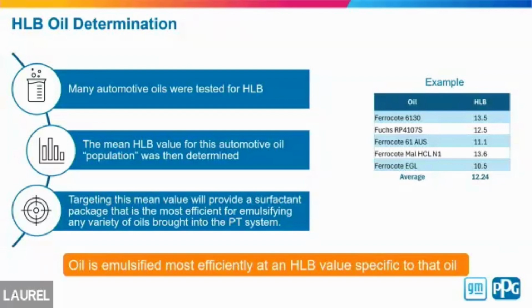So how do we identify this average? We cannot screen all the oils available in the industry. We select a larger pool of these oils. And there's a theory that the larger the pool within a set of oils, the closer the average is going to be to the full average of the pool of oils. So basically, first we identified the HLB for each oil. We look at the average, and that's the target we are aiming for, looking for our surfactant package.